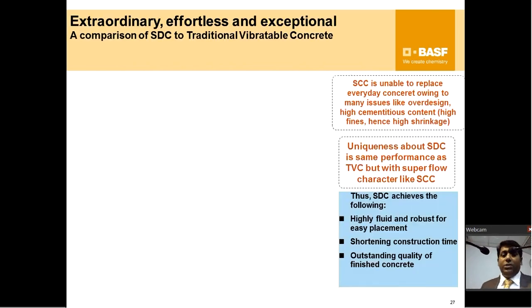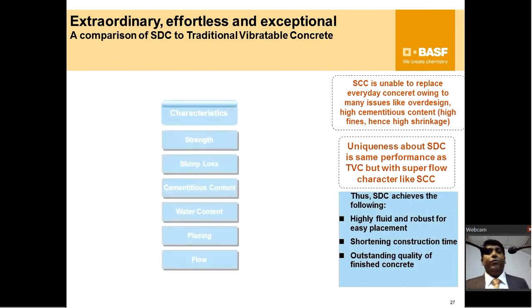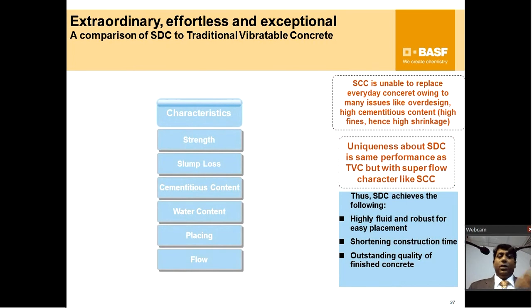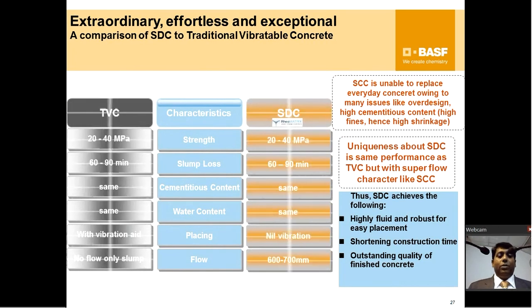So what are the salient features here? How is it different from traditional vibrated concrete? Here the strength is 20 to 40 MPa, both are the same. Slump loss is the same, 60 to 90 minutes. Cementitious content almost remains the same, not much change. Water content is the same. Your traditional vibrated concrete needs to be vibrated, but this needs no vibration at all. Your traditional vibrated concrete doesn't flow, it gives you a slump. Here it gives you 600 to 700 flow.